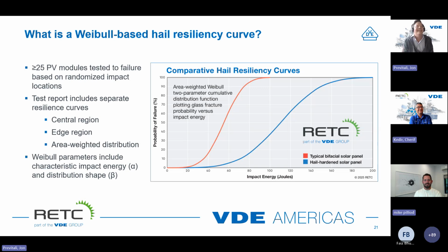I can explain it. So we developed this Hail Resiliency Curve Test. As we were talking about, it's a test to failure where we require at least 25 PV modules, ideally randomly selected from a batch of modules representing a particular bill of materials, or a set of components manufactured at a particular location, or at least having enough significance or difference from other bills of materials to be a distinct bill of materials. So we take at least 25 of those modules, up to 30.